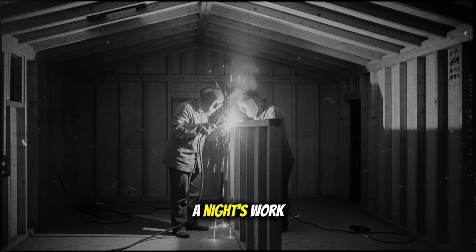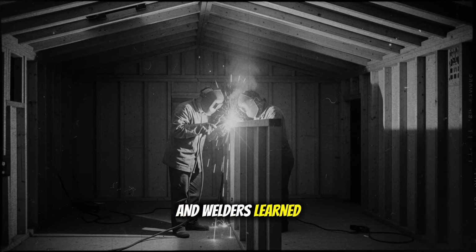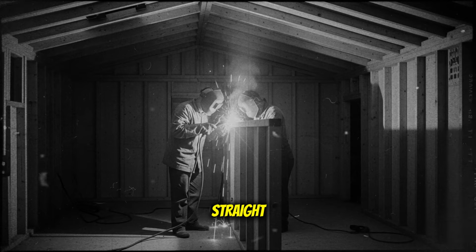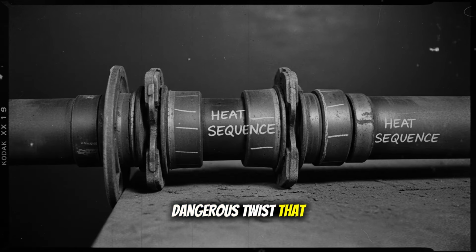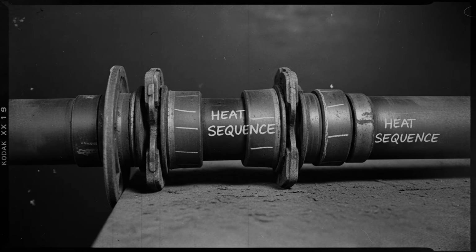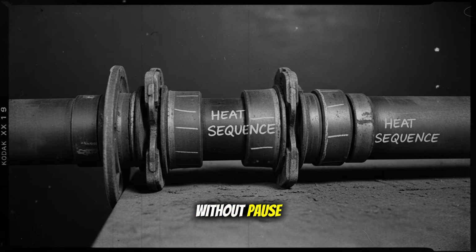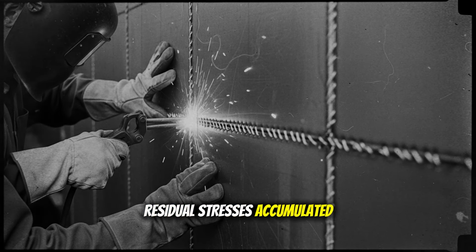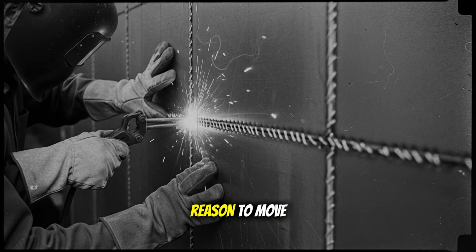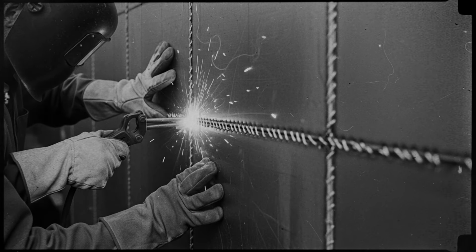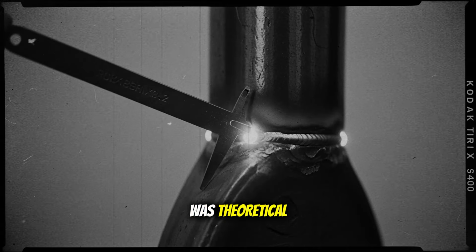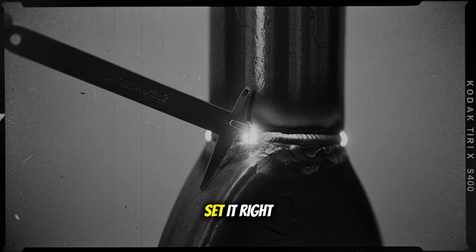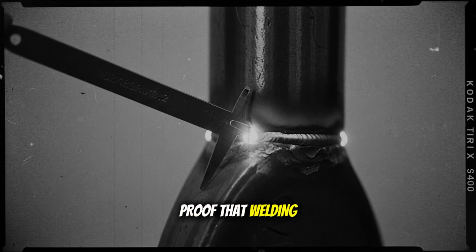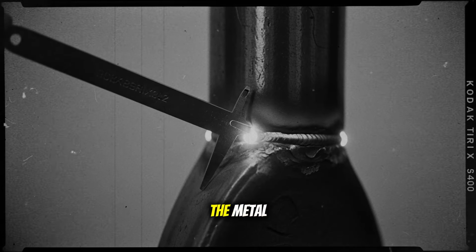Inside the prefab shed, a night's work began with a hiss and a bloom of light, and welders learned early that the order of their beads could teach the steel to lie straight, or to pull itself into a quiet, dangerous twist that no level could deny by morning's inspection. When a long seam was run from one end to the other without pause, cooling contraction tugged the plates into a bow, and even when the eye could not see the curve, residual stresses accumulated along the weld toe like ghost loads waiting for a reason to move when cold seas and hull bending gave them one. The discovery was tactile before it was theoretical: set the sequence wrong and the panel warped under your gloves, set it right and the piece relaxed into place, proof that welding is not only joining but also writing invisible history into the metal with every heat cycle and every pause chosen by the torchman.